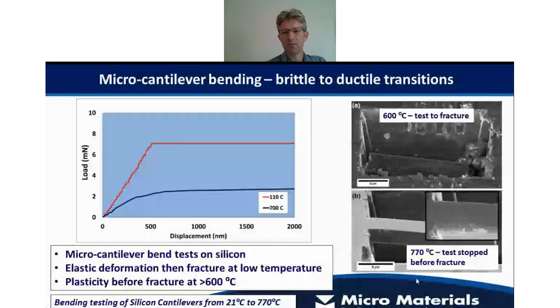When they've done these types of tests at Oxford University, they were able to pull out differences in elasticity, but also differences in ductility. The red curve shows a typical example of fully linear elastic bending, and then suddenly a fracture at very low temperature. And at high temperature, above this brittle-ductile transition, we get a much more ductile behavior before it fails. Indeed, you can actually see slip lines in tests at high temperature stopping before fracture, as shown on the right.